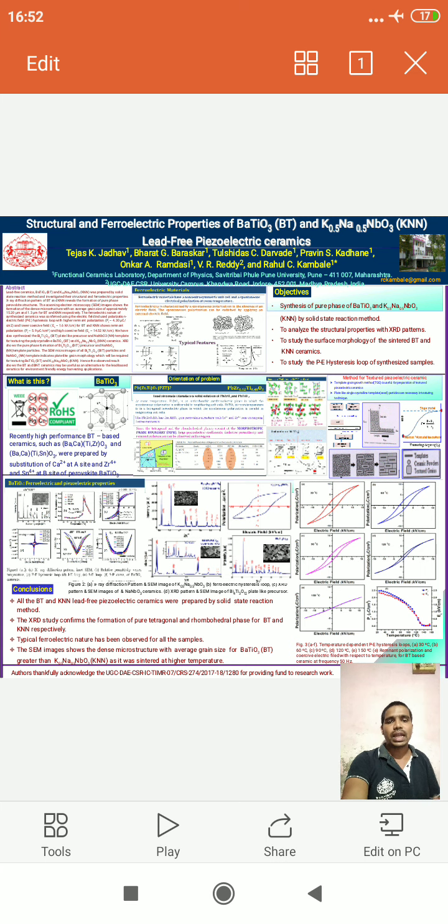The next diagram is the dielectric constant versus temperature. In this diagram we can see a higher maxima point, the peak. At that peak we can calculate the Curie temperature for the ferroelectric material, and also the higher dielectric constant. But when you increase the temperature above the Curie temperature, the ferroelectric material becomes a paraelectric material.